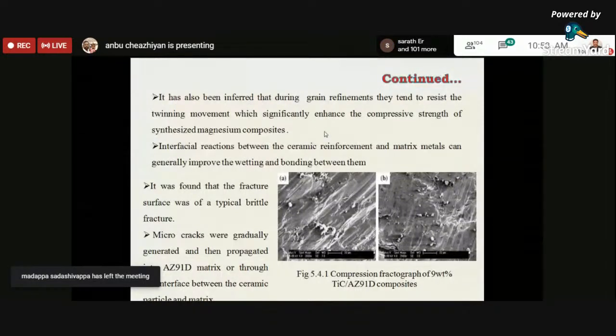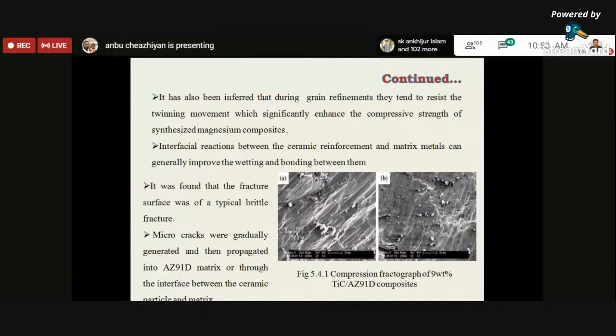These were the same images. It is seen that the titanium carbide particles can still be seen in the same images, so they have not completely dissolved. They appear as fine globular particles in the matrix material. We can also say that due to the cushioning effect, it is able to withstand the load, and hence the compressive strength also increased.